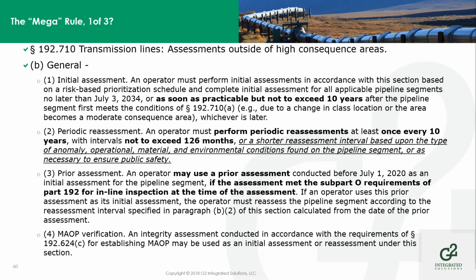In general, the operator must perform initial assessments in accordance with this section no later than July 3rd, 2034, or as soon as practicable, but not to exceed 10 years. You must perform a periodic assessment at least once every 10 years thereafter at intervals not to exceed 126 months. There's that grace period. Or shorter reassessment intervals based on the type of anomaly. If there's issues found on the pipeline that say you need to look at it more frequently, then of course you would do that. And you may use any prior assessments conducted before July 1st, 2020 as an initial assessment